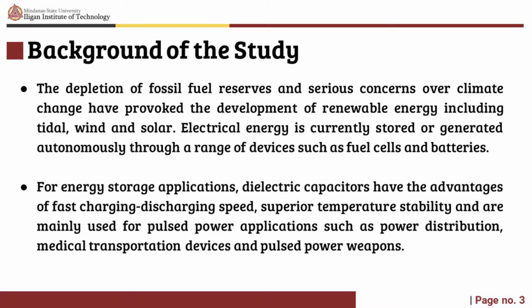Dielectric polymers are limited by their low melting temperatures and related degradations. Dielectric ceramics are potentially more temperature stable than dielectric polymers, but have comparatively low recoverable energy density, or WREC, and energy conversion efficiency, or η, due to their low electric field breakdown strength, which is BDS, and high energy loss, or W loss.